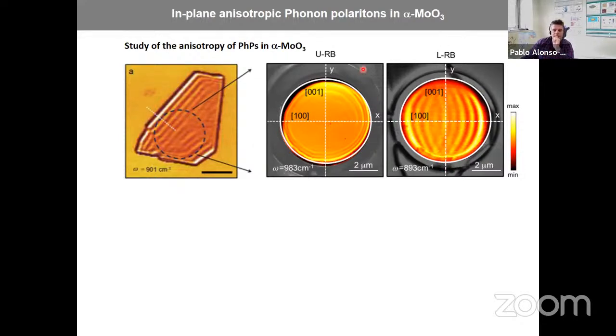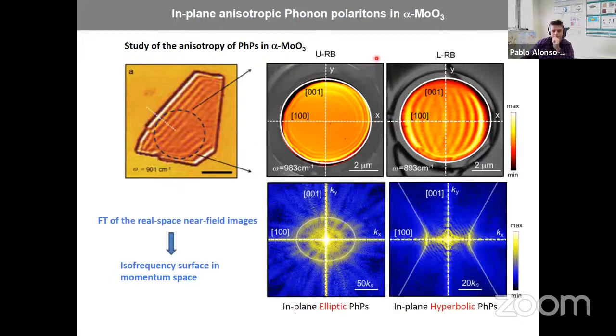To see better this kind of propagation, we can do the Fourier transform of this real space image. And then you see these plots here that are called isofrequency curves. Isofrequency because they're given at a fixed frequency, and it's in momentum space, right? So this is kx, ky. And this is all the directions that are available for propagating polaritons. Here they are elliptical. And in this other case, because of this strange real space shape, when one does the Fourier transform, you can find here a hyperbola. So this is what is called hyperbolic propagation of polaritons, and these are hyperbolic phonon polaritons.